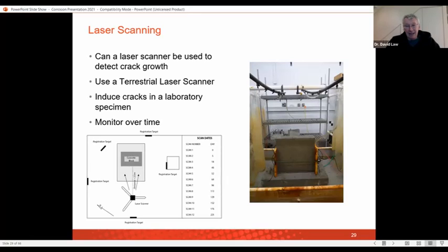Another interesting technique that we've been using is to look with a laser scanner to try and detect deterioration on a structure. So we had here a block that we put in the laboratory. We're actually corroding this by applying a current to make it corrode faster and spraying it. And we are monitoring over time using a terrestrial laser scanner. We also went down and actually scanned a seawall as well to see what was happening on a real structure.